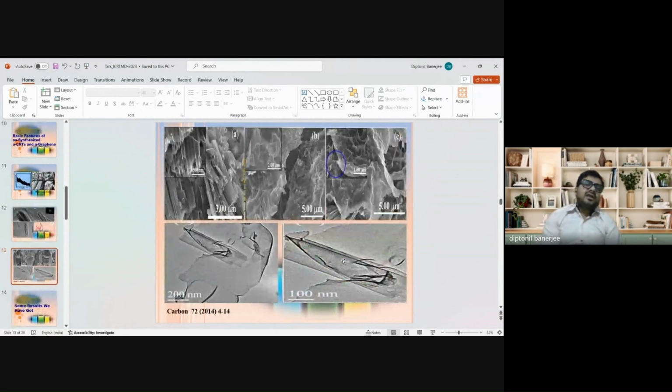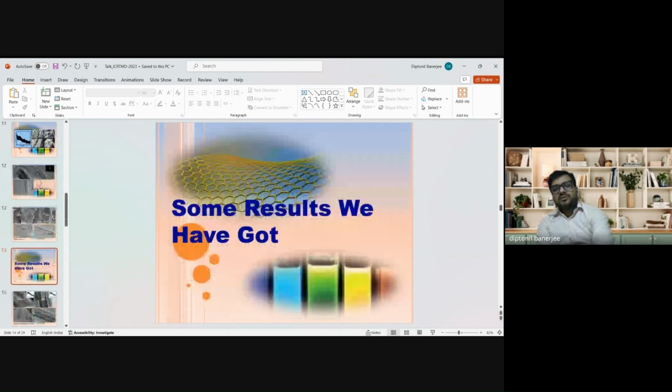And when these amorphous carbon nanotubes are unzipped by just 1 to 2 hours of ultrasonication, they get unzipped, and a graphene-like two-dimensional structure can clearly be seen. With this, we can produce very good CNT graphene composites that show very good cold emission property, and you can see that it is already published in the journal Carbon.